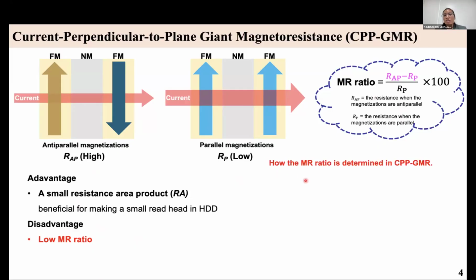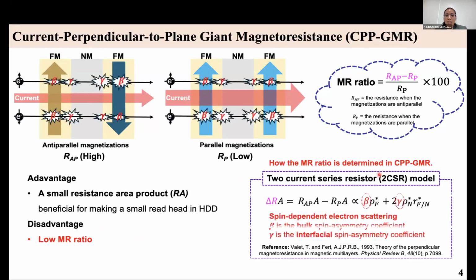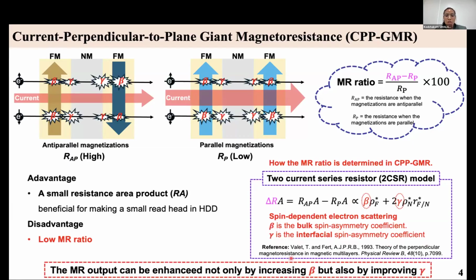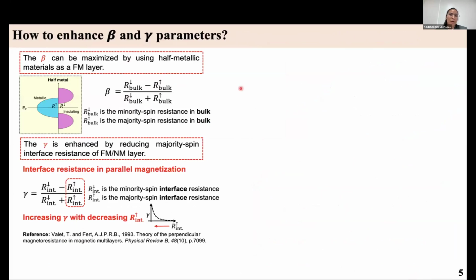So how is the MR ratio determined in CPP-GMR? It is determined using the two-current series resistor model, which can be described by this equation. There are two intrinsic factors related to spin-dependent electron scattering that influence the MR ratio. First, beta is the bulk spin asymmetry coefficient. Second, gamma is the interfacial spin asymmetry coefficient at the interface. So from this equation, it is evident that the MR output can be enhanced not only by increasing beta, but also by improving gamma. So the key question becomes how to enhance beta and gamma parameters.